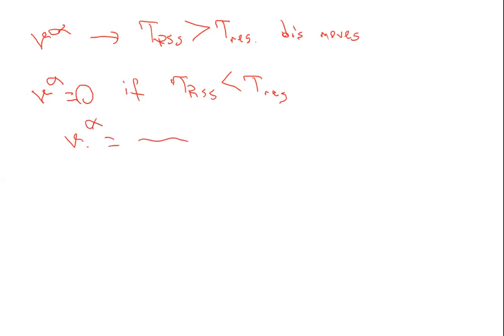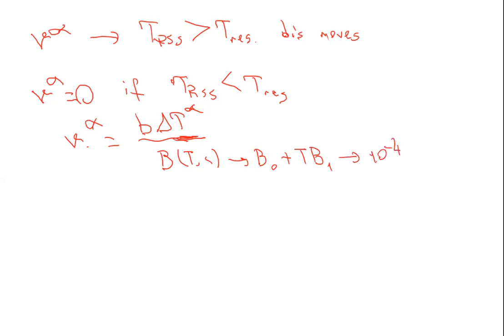And velocity can be calculated through the Burgers vector times the shear stress at each slip system always divided by the drag coefficient. And this drag coefficient is a function of sometimes temperature, sometimes if you have additional solutes in your material, C, and we have B0 plus T B1. And if you go ahead and check some papers, you will see that it is on the order of 10 to the -4.